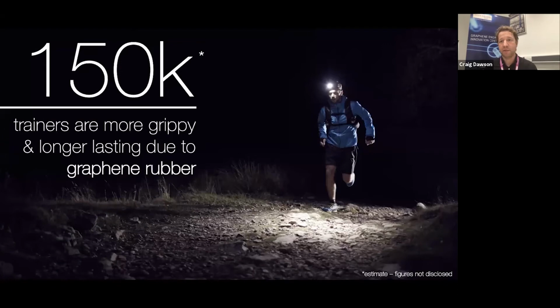This is a University of Manchester collaborative project where we worked with a company called Inov-8 trainers, and they've put it in their rubber. Usually you trade off wear against grip, and by adding a small amount of graphene, they've been able to improve the wear without trading off the grip. So they've got a grippy trainer that lasts twice as long. And the question is, why would they want their trainers to last twice as long? It's more sustainable, but also they managed to sell twice as many trainers because of the addition of the graphene.